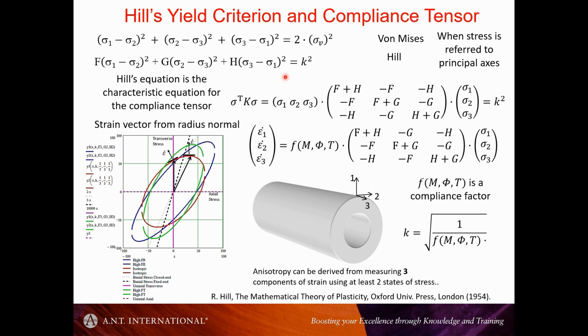as in terms of a stress, it would be the stress divided by the modulus, by the Young's modulus. In that case, the energy input is basically in terms of a stress squared. So you have this stress squared criteria, and Hill had a kind of similar expression. It's not called a von Mises stress. He would do it in basically, you could either call it K, single K, or K squared. It doesn't really matter. But at some point the energy input leads to yielding.